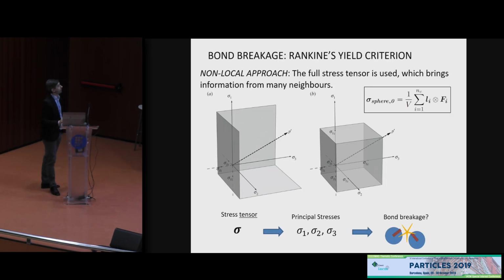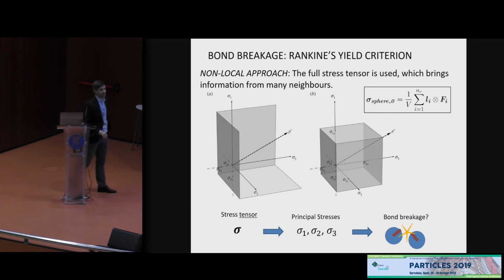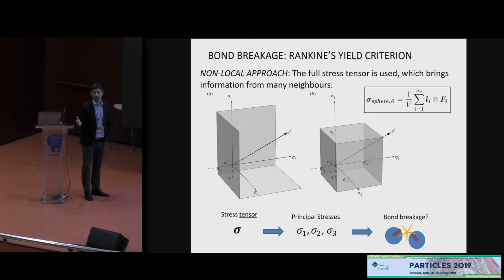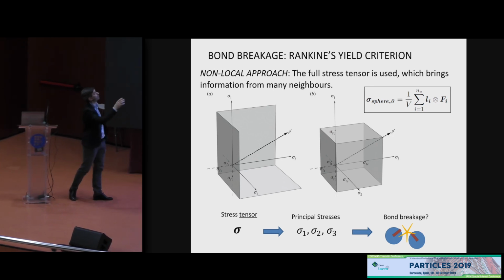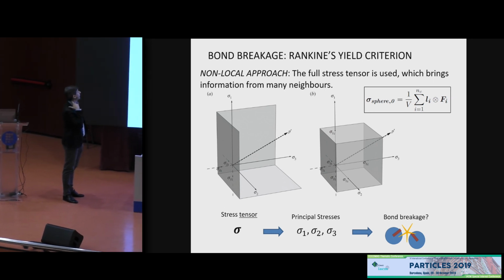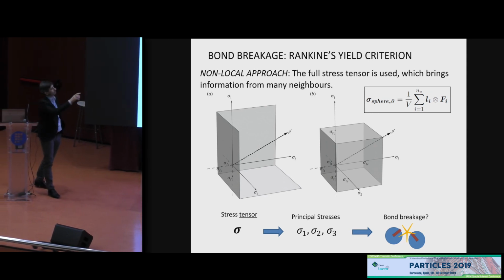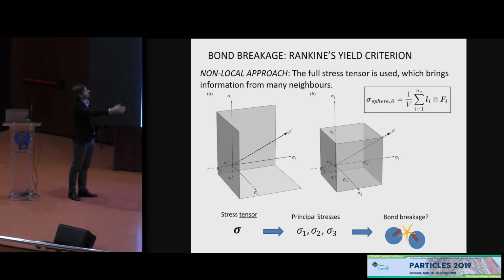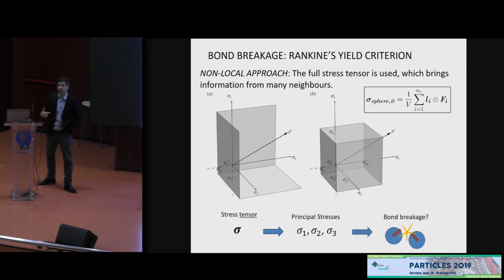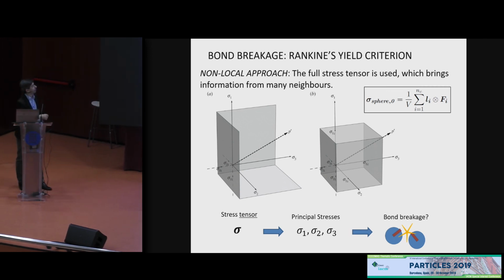However, our idea is to use typical yield surfaces from continuum mechanics, for example, Rankine's yield criterion. And our proposal is to use a non-local approach. The full stress tensor can be used. We have it. That's the formula that I put before, and that's the value that we are feeding into the forces formula.